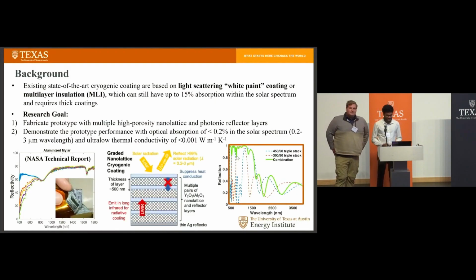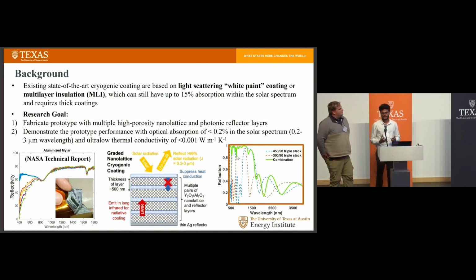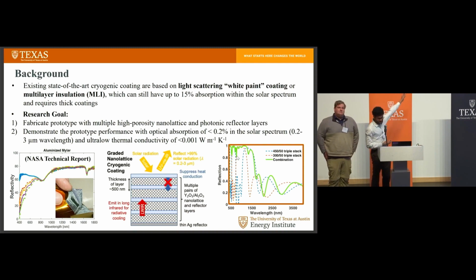There are existing state-of-the-art cryogenic techniques which are used to store hydrogen in storage tanks, but there's a problem of hydrogen boil-off, which basically refers to the vaporization of hydrogen into its gaseous phase from its cryogenic liquid state. There are existing techniques involving white paint coating or multi-layer insulation, which can still have about 15% of absorption, as you can see from this left-hand side bottom image from NASA's report.